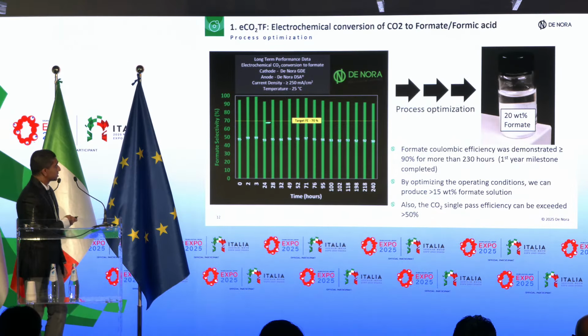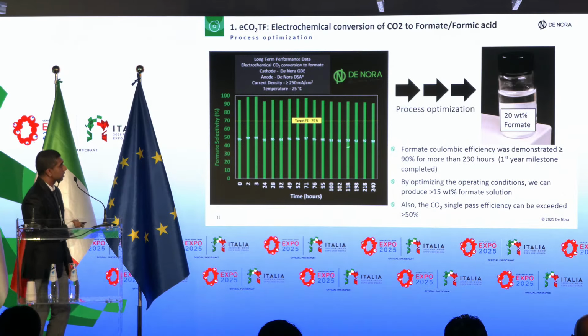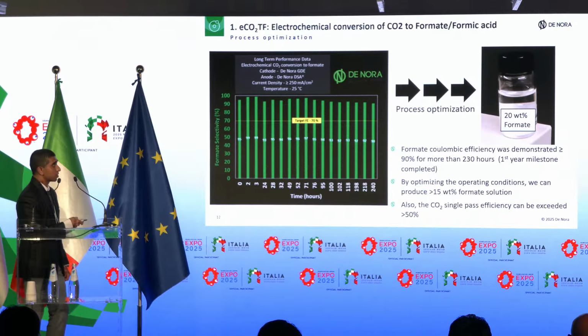We also did some process optimizations and collected data for a long duration. What you see here is the formate selectivity versus the time we tested this system. Our project target was to maintain 70% Faraday efficiency for formate, but you can see we ran it over 200 hours at this current density. By doing process optimization, we were also able to make about 15% formate solution. During this process, we also demonstrated that our carbon dioxide single pass efficiency can exceed 50%.